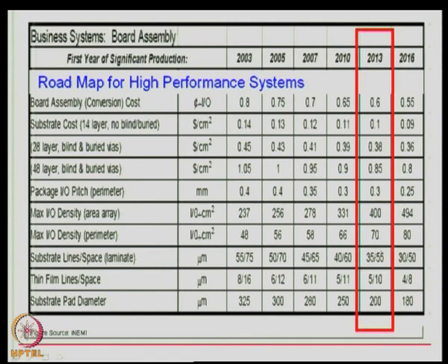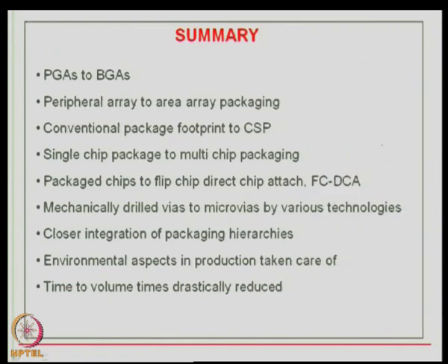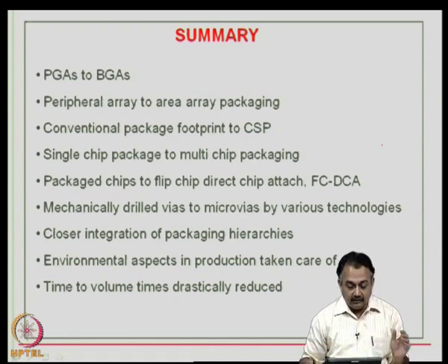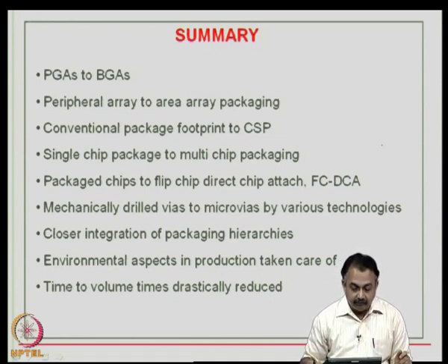Substrate line and space, for example, 35 micron, 55 micron space, thin film lines 5 micron and 10 micron space, substrate pad diameter is 200 microns, area array maximum IO density is 400 IOs per centimeter squared. That is the kind of density we are looking at. So, if you look at multi-layer systems again, the cost has to come down even as we increase the multi-layer structures. So, summary for this chapter on packages is that, if you have gone through the various sessions that this package has encapsulated,